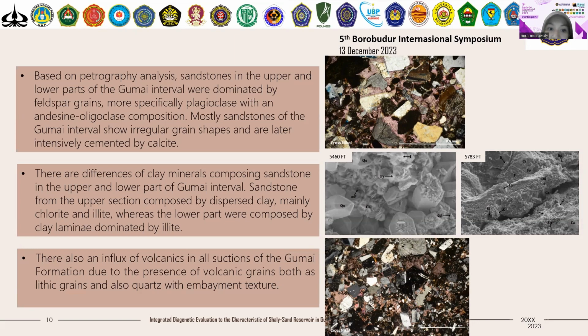Sandstone from the upper section is composed by dispersed clay, mainly chlorite and illite, as we can see by here. It is chlorite and it is illite, whereas the lower part were composed by clay laminae dominated by illite. We can see the occurrence of illite, abundantly illite, composing the sandstone. And there is also an influx of volcanics in all sections of the Gumai Formation due to the presence of volcanic grains, as we can see by here, both as lithic grains or as embayment quartz.